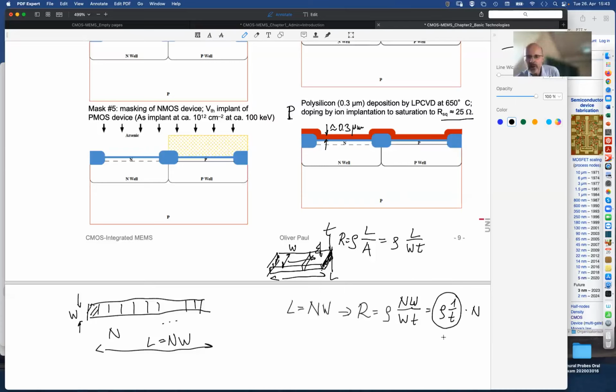And so this particular construction is called the square resistance or sheet resistance. You only need to know the resistivity and the thickness of the material. Then the design only boils down to the aspect ratio of the line, not to the absolute dimension. So a line that is 1 micron wide and 100 long has the same resistance as one that is 10 micron wide and 1 millimeter long. There's 100 squares in both of them. That's why the square resistance is very useful. So the square resistance or sheet resistance of polysilicon is 25 ohms.